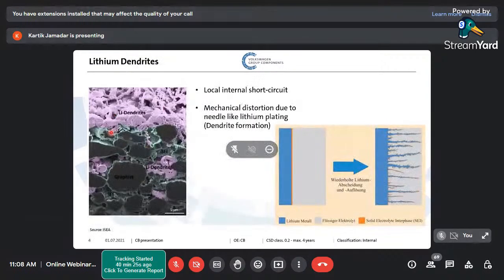So you can see this is a dendrite structure, which is produced mainly on the anode side because of the non-uniform deposition of lithium, and these dendrites would eventually make a short circuit. People tried many different ways to change the electrolyte. One line of research went into the polymer electrolyte. They found that polymer electrolyte is somewhat better against dendrites. Another line of research went into solid state batteries, with a non-flammable solid electrolyte, which we call a ceramic based electrolyte.